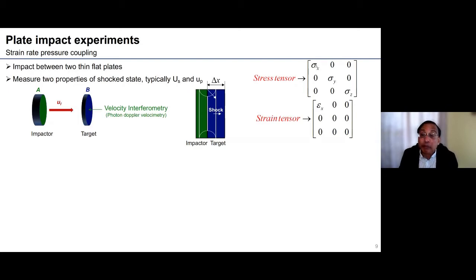If you use the Tresca condition, for example, the strength of the material could be an order or a few orders of magnitude smaller than the pressure. So this poses great challenges in measuring the strength of the material, because it's a small number in comparison to the pressure of the material. So you need a way of directly assessing the strength of the material at these high pressures.